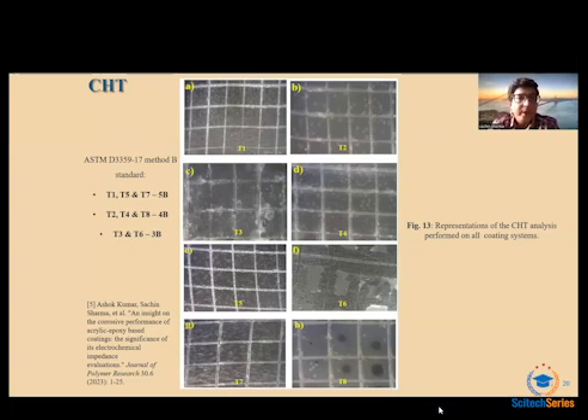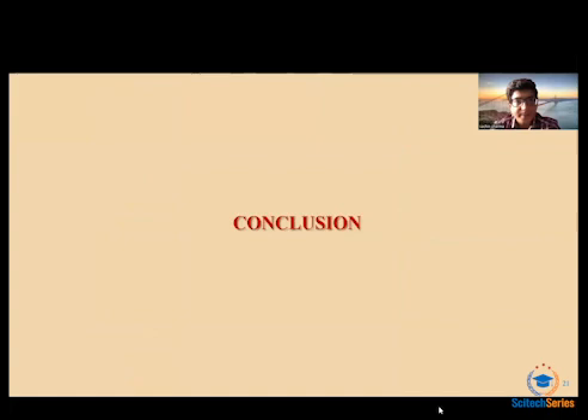All the results exhibited in the CHT were in complete agreement with the water contact angle results, the EIS, as well as the breakpoint frequencies, which indicated why the samples containing the highest acrylic content exhibited the best results.